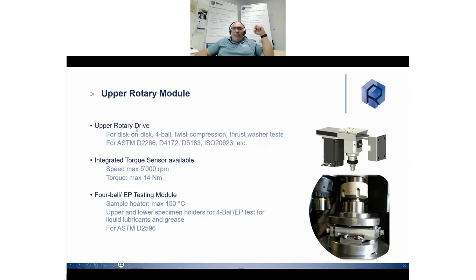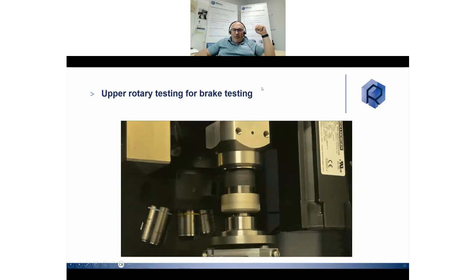With an upper rotary drive, we can do disc on disc, 4-ball, twist compression, thrust washer, a lot of testing. We can go up to 5,000 RPM with a max torque of 14 Newton meter. And the idea is in fact to block the lower part in order to maybe control the temperature environment differently. You see a small video.